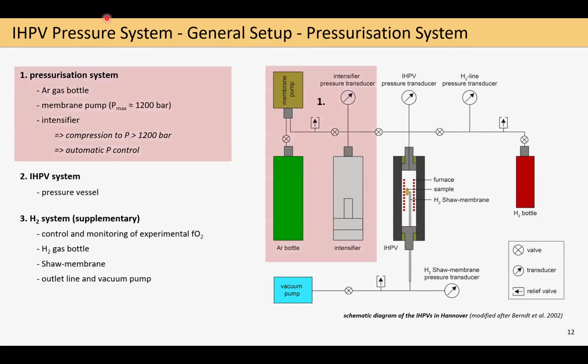But first, let's start with the pressurization system, which, as the name says, is there to pressurize our experiment. It consists of an argon bottle, so the gas reservoir, a membrane pump to pre-pressurize the entire system, and then a so-called intensifier, which we use to first compress the vessel to higher pressures and also control pressure automatically during the experiment. And you can imagine the intensifier as a small reservoir which is connected with the vessel during the experiment and equipped with a hydraulic piston which can drive in and out of this volume, thereby decreasing or increasing the real volume, so changing the pressure. So a relatively easy but efficient system.